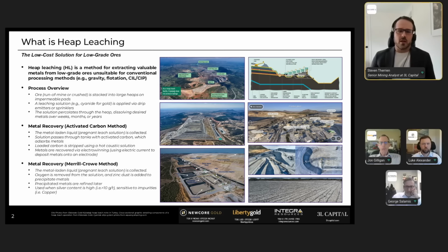So heap leaching is a processing method, if you're not sure, for extracting metals from low-grade ores that cannot be economically processed using conventional methods like milling. The process involves stacking run-of-mine or crushed ore onto large heaps on impermeable pads, followed by applying a leaching solution through drip emitters or sprinklers for weeks, months, or years. As the solution percolates from the top of the heap to the base, it dissolves the desired metals, which are then recovered from the metal-laden liquid known as the pregnant leach solution.